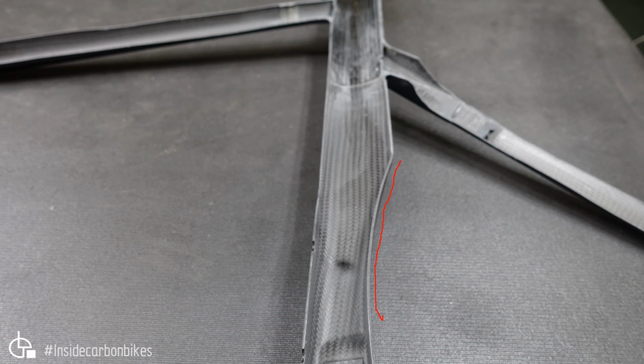However, often your fiber density, particularly because you're using a woven material, is going to be less than a unidirectional prepreg material. Typically you're running fiber volumes of maybe up to 60% with a woven, whereas you can get close to or even over 70% with a well compacted unidirectional laminate. So you are running a little bit higher resin content, but you're reducing voids and things like that. There is a bit of a trade-off in the mechanical properties.